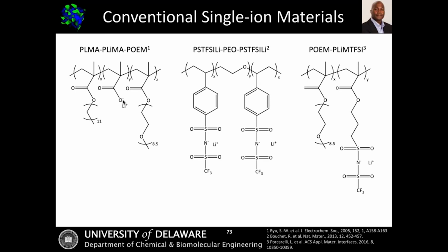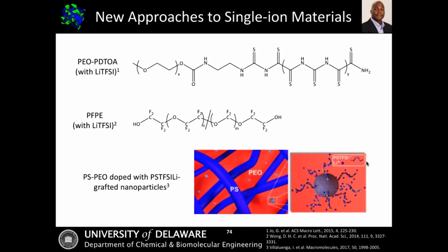Now, in all of these cases, what they look at is not just conductivity, but transference number. And what does that mean? Just really briefly, in transference number I'm really interested in the motion of lithium, which is the ion that's of interest. And I have to be very careful when I think about conductivity, because in many cases when I'm measuring conductivity, I'm not just measuring the lithium, but I'm also taking into account the anion that is moving also. So in these potential solutions, where the anion is tethered to the polymer chain, now only the cation is mobile, which can really allow me to improve the performance of my materials. So in the last couple slides, I just want to mention a few things.